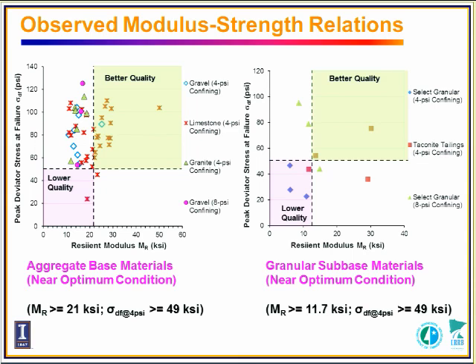So the information to catch here is that the modulus-strength relationship is not unique for aggregates. The better indicator for their performance is, I think, the shear strength indicator, as Professor Thompson emphasized before, that rutting behavior is a primary indicator of unbound aggregates. So modulus, if we just look at the modulus, sometimes can be misleading.